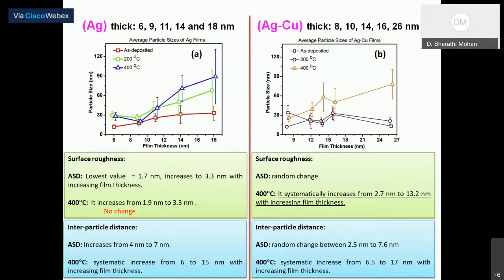And we have analyzed these films and calculated particle size, surface roughness, and interparticle distance. Overall, the particle size is increasing with increasing film thickness and increasing the annealing temperature because of the increase in the crystallinity of the silver films.